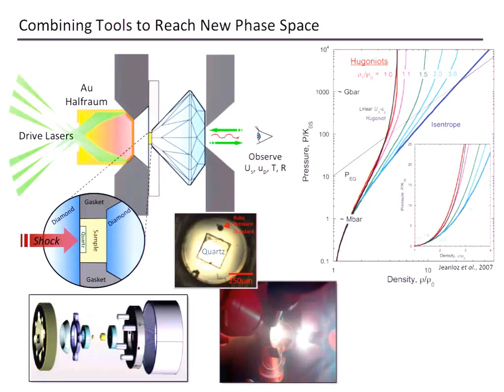This is a picture of one of the diamond cells getting shot at Omega. We use quartz as a standard material to impedance match, and there's a ruby that we use to measure the initial pressure in the sample. In this case, this is about 400 microns in diameter or so.